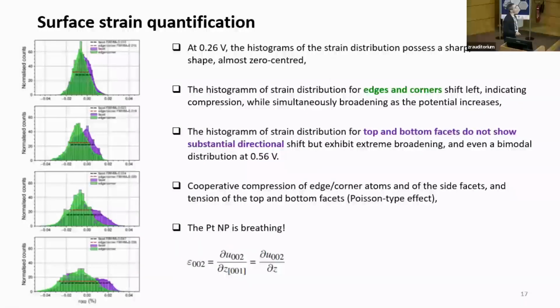You can better see this on this histogram of surface strain distribution. What you see is that on average, the histogram of strain at the edges and corners is broadening and shifting negative. So we are compressing the edges and corners. And for the rest of the facets, there are different behaviors. For example, the side facets are compressing a little bit, and the top and bottom facets are expanding when we increase the electrode potential. So everything is very heterogeneous, and there is a different behavior in every different location of the particle.